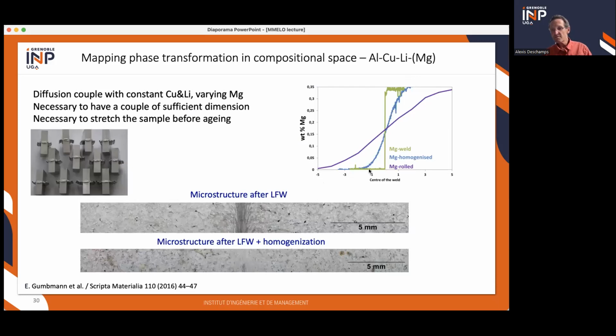If you're not ready to wait forever, then you sometimes have difficulties getting a gradient over a sufficient distance, because with the spatial resolution of X-ray experiments, you're not necessarily able to have many data points within a couple of millimeters like here. So you can extend it by rolling, for instance. After rolling, we got a gradient between 0 and 0.3% of magnesium over almost 10 millimeters. So then you have a very nice microstructure, constant aluminum, copper, lithium, and varying magnesium.